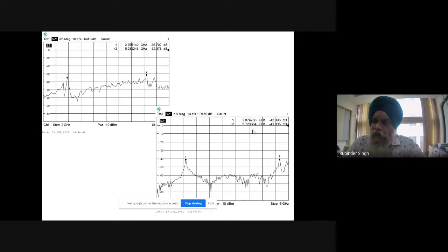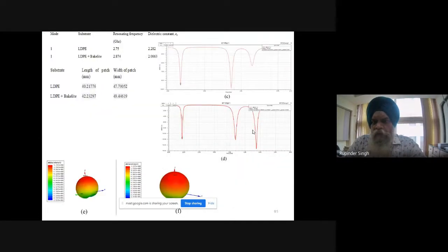So we initially selected an epsilon r value of 3, and we calculated using this VNA analysis. We calculated that the dielectric constant of this material was coming to 2.2 and 2.0 for the combination, and based upon typical VNA analysis, we calculated the dimension of the patch in the form of width and length. But we observed, once I add the bakelite into it, there was a marginal increase in the dimension. You can see earlier it was 40 and 47. Now it was increased to 42 and 49.